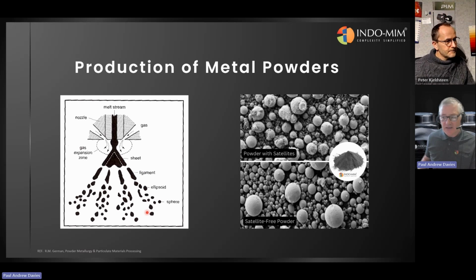Exactly. So these particles, depending on the process gases, can recirculate and float around, and eventually, because they're solid and often very fine, they can end up solidifying on the surface of larger particles, which is why you can see some of the larger particles have little satellites attached, because they basically stuck to the surface as it was solidifying. So having a narrow, finer distribution can help solve that problem. But yes, having additional processes like this secondary anti-satelliting gas ring can help to avoid that and blow the fines to the side of the chamber where they're then collected. Stay away. Exactly.